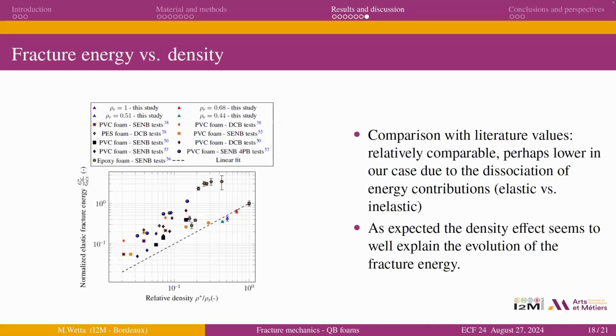The last result concerns the diagram and the evolution of the fracture energy as a function of the relative density. As was expected, we have a good link between the fracture toughness and the relative density. The relative density explains very well the increase of the fracture energy, as Ashby and Gibson highlighted before. And probably the difference compared to the literature data is explained by the inelastic part, which is most of the time not taken into account.